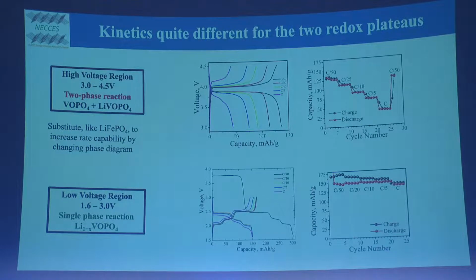You can see in here there's really no difference from 50 hour to 1 hour. Extremely high rate. The difference is in here, again, just resistance of the electrolyte. So we've got extremely high rate for that low voltage region, and that's a single phase reaction. You can see these bumps in there, that's where the lithiums are trying to order themselves. So we have to solve the rate problem.